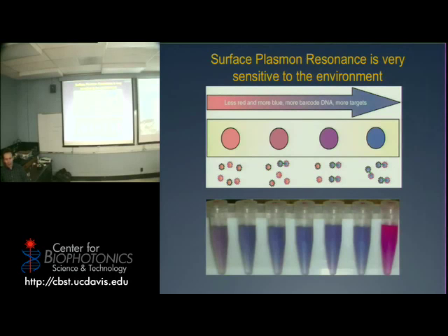And yet again, what is the only thing that is different between the 2 particles? Size. It's the size. So why do you think there will be such a difference between the 5 and the 20 nanometers? Exactly. It's the surface area. So these objects are tiny, really tiny. We're talking about, especially the 5 nanometers, maybe, I don't know, less than 1,000 atoms. So the amount of atoms that are on the surface compared to the actual volume is humongous. And this ratio, the surface to volume ratio, obviously decreases as the particle goes up.